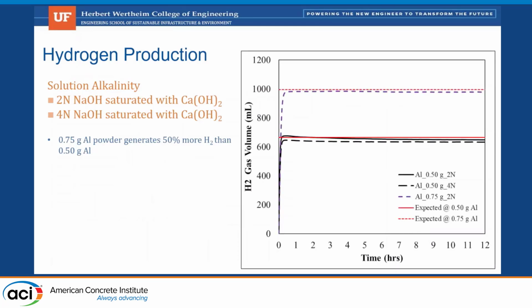When we look at that, we have what is an expected line of hydrogen gas production if we use a perfect equation. And then we have the stuff we're getting in the lab. What we found is we can measure all the hydrogen gas produced from an aluminum source. That's an experiment that collects the hydrogen gas formed in a liquid container that we've developed. The red lines give us our expected, and we're about 5% error. I'm pretty happy with those numbers.